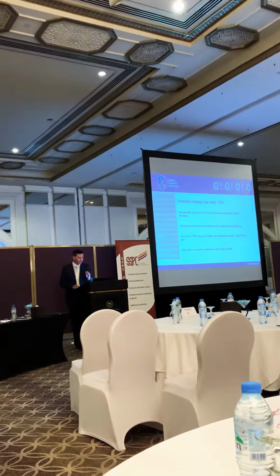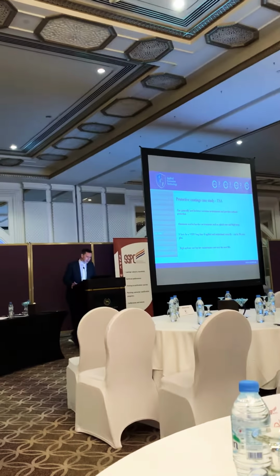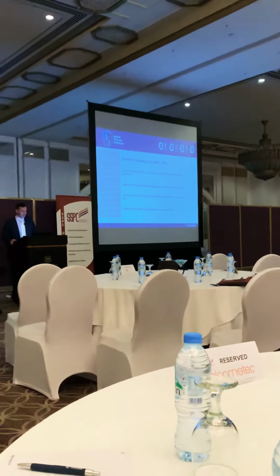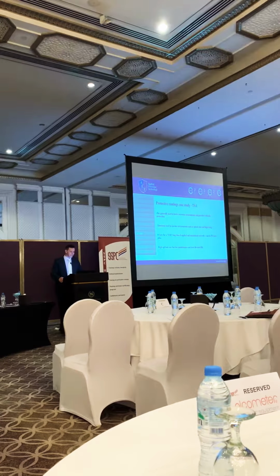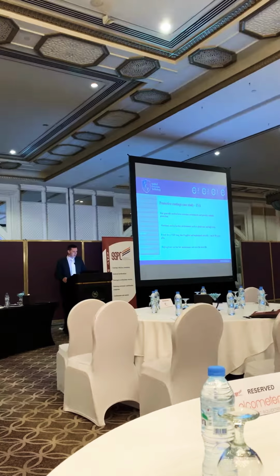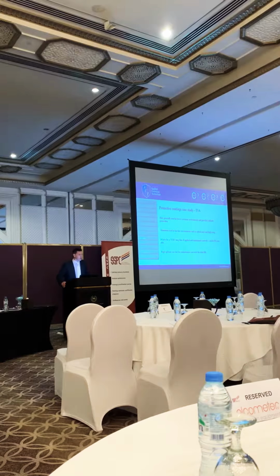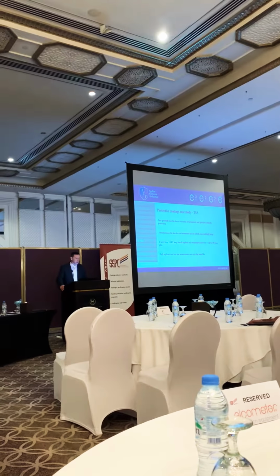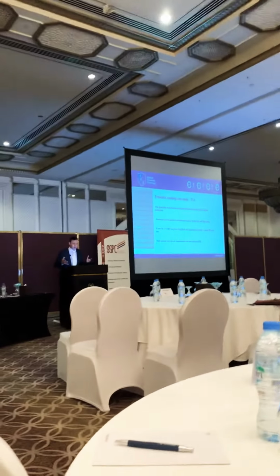So I hope that gives you an idea of the application process. So a little bit of technical about how we go about selecting TSA, or I keep saying TSA, thermal spray. TSA is thermal spray aluminium, could be thermal spray zinc as well. But zinc we find is generally used in lower corrosion environments, and it provides a product protection element. TSA is usually used in harsher environments such as splash zone and high temp, which for this room is probably the more appropriate medium that would be used for most projects.